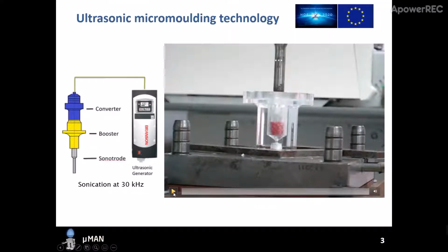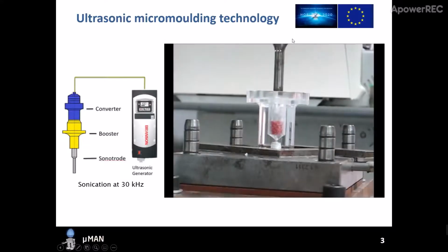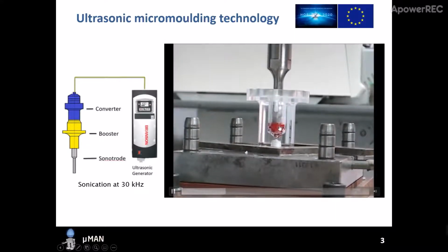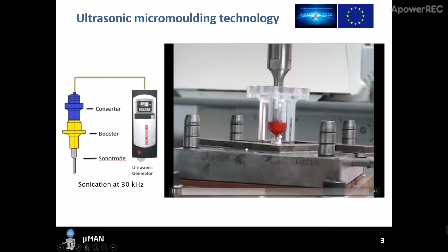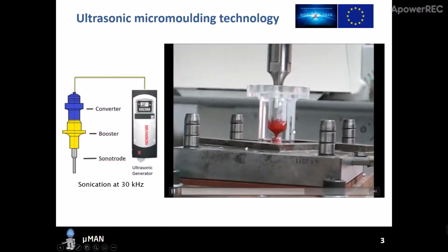As you can see from this video, the sonotrode moves down, vibrating and melting the polymer using interfacial friction and viscoelastic heating mechanisms. We don't use any cartridge heaters or other heating mechanisms to melt the polymer, but we use only ultrasonic vibration to melt our material.